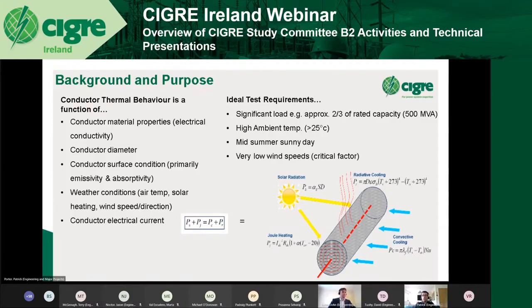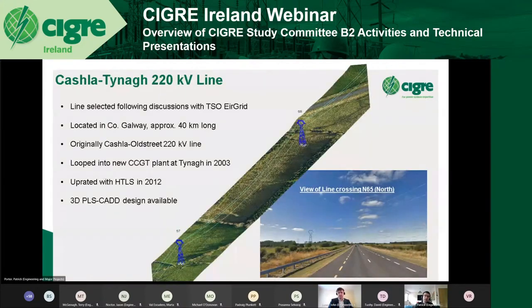So we know that for a high temperature test, the ideal test requirements would be a significant load on the line, so we needed at least 2/3 of the rated capacity. We wanted a high ambient temperature, ideally above 25 degrees Celsius, so that was likely to be a midsummer sunny day. And then the last factor, which is one of the more critical ones, is low wind speeds. And that's just something that we'll touch on in a few slides.